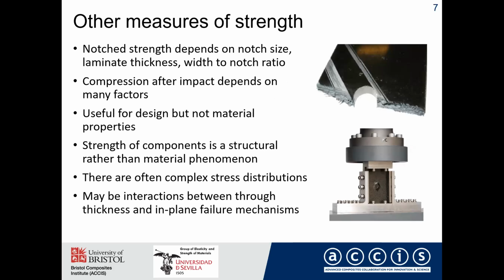If you look at things like notch strength, then this depends on all sorts of other parameters: the laminate thickness, ply thickness, stacking sequence, laminate width to notch ratio, all sorts of additional parameters. And compression after impact also depends on many parameters. So these are useful tests which should give useful information for design, but they can't be considered to be ultimate material tests. They're not generating material properties. They're generating useful values which can be used in designing.